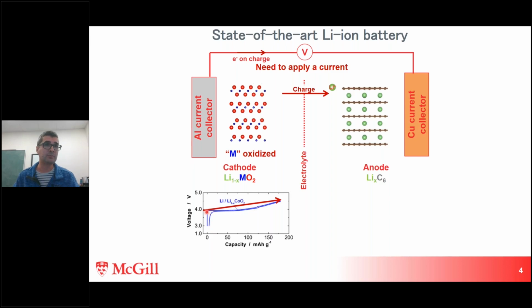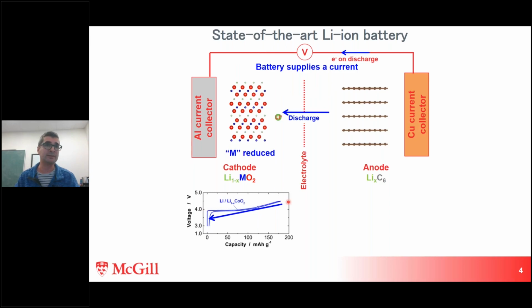So when we charge it, the voltage increases and we get a plateau at a certain voltage. And this corresponds to the redox of the transition metal. So in this case, cobalt gets oxidized from 3+ to 4+ at this voltage of 4 volts. So that's why we have a plateau here. And then it increases to whatever we choose as our maximum voltage. And then we turn around and discharge it, and it comes back down. And lithium returns to the cathode. So that's the secondary battery. That's why it's reversible and we can charge it and use it over and over again.